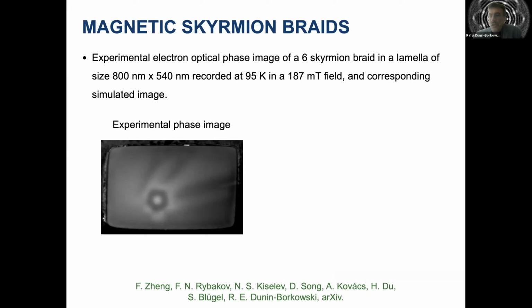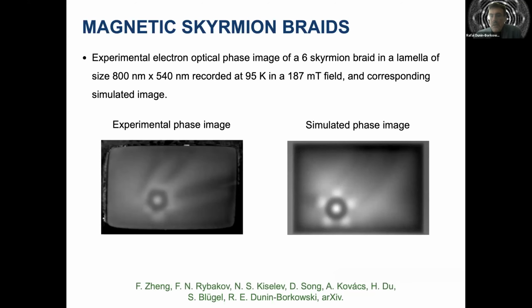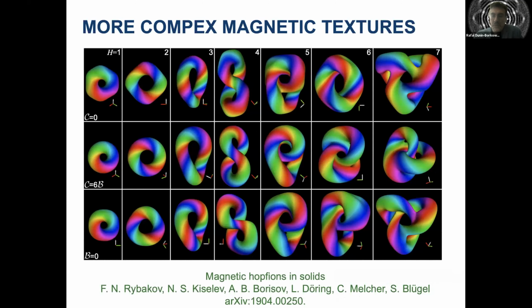And a simulation of one of these superstructures, which is braided, where the magnetic skyrmion strings twist around each other, reproduces this curious structure. And so this is a direct experimental verification, viewed in one direction, of this skyrmion braid, but again, it's never been observed experimentally in 3 dimensions before. And finally, there are predictions of even more complicated magnetic states, which are referred to as magnetic Hopfions.